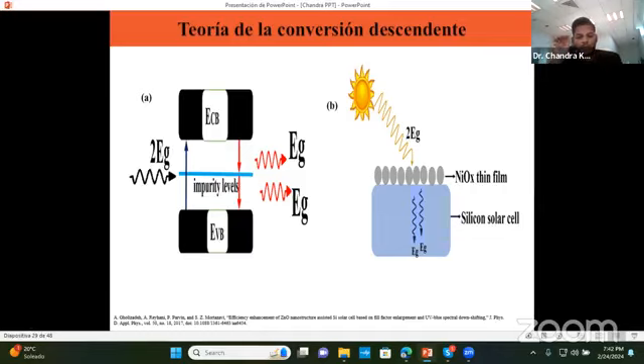So a high energy photon, like the one given here, has energy equivalent to 2 EG. If we are talking about silicon, the band gap is 1.2 electron volt, but the sunlight coming has energy around 2.4 electron volt, equivalent to two photons. So obviously, if the coming light and the band gap are not matchable, then that light might be reflected back. In that case, we have to put one layer over the material to convert this high energetic photon into a different photon.